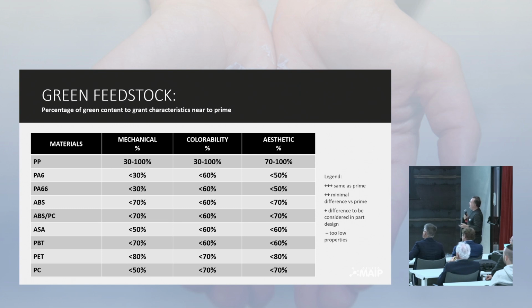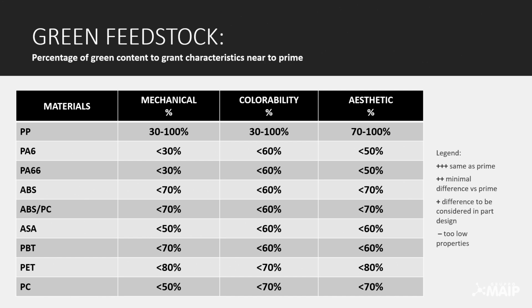This is a fast description trying to tell how much material coming from mechanical recycling I can use to grant properties which are similar to prime. So in some cases, in the case of polyamide, the amount of recycled material, if you want to grant mechanical properties close to prime, is not so big because of the titanium dioxide which I was mentioning. 70% of polyamide recycling is coming from the textile industry, which unfortunately is adding, for different reasons, titanium dioxide, which is breaking the fiber. There are other materials for which you can use a higher amount, like PBT and so on, or ABS-PC, in which you can use almost 100% of the polycarbonate component coming from recycling.